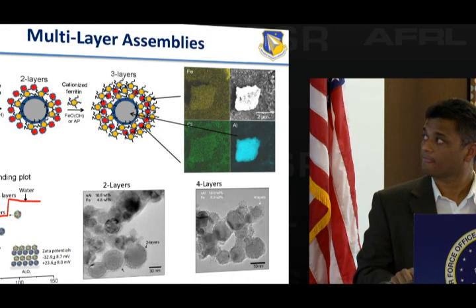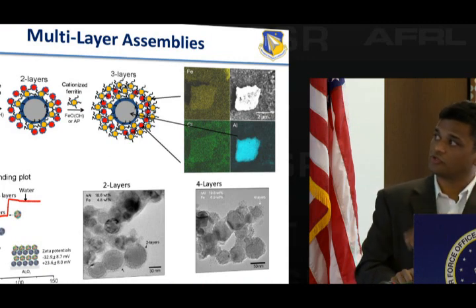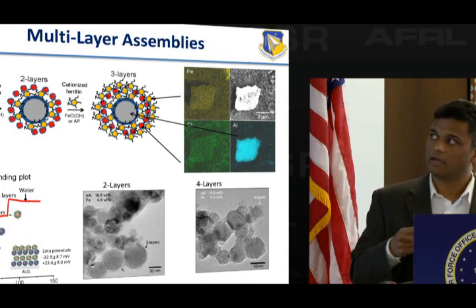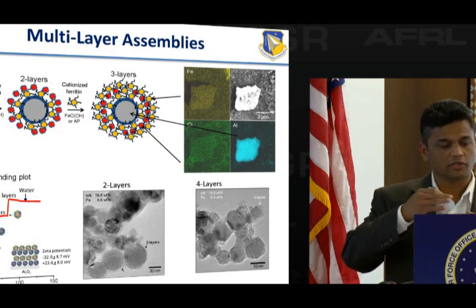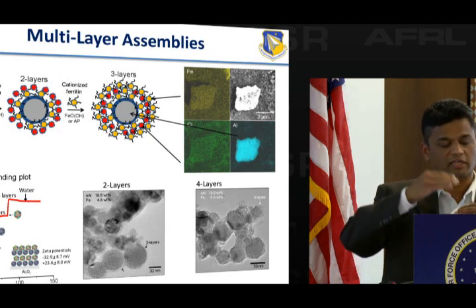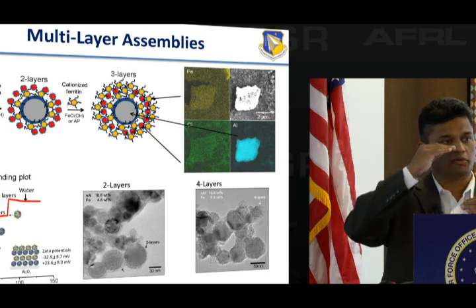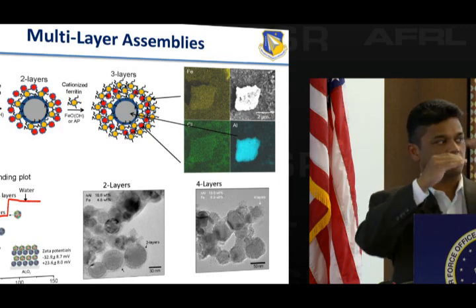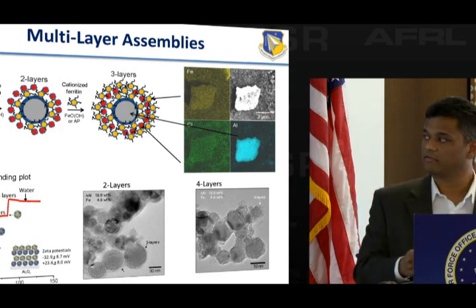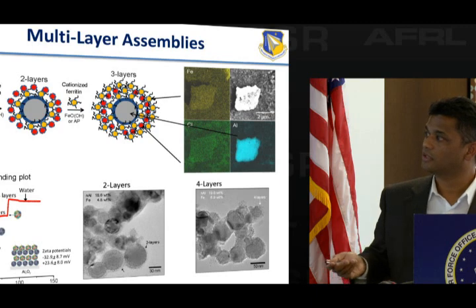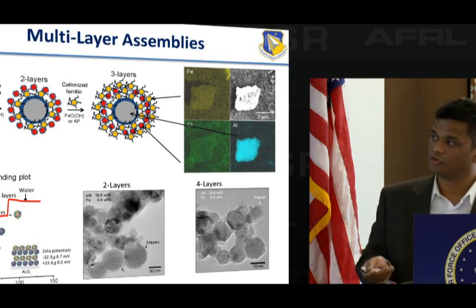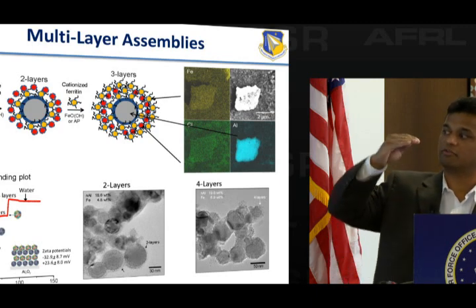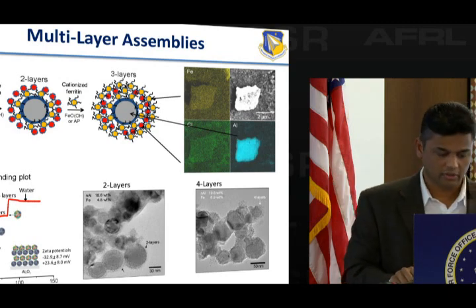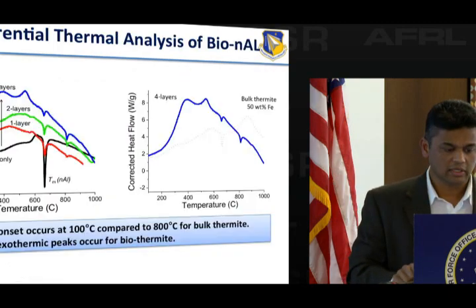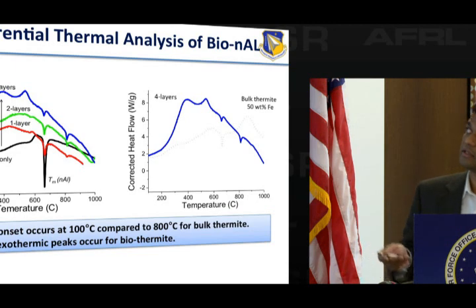We have done EDS mapping to show things, but we've been able to show that you can not only create one layer, you can use rational design to create multiple layers. You can put ferritin, you can put ammonium perchlorate, you can put ferritin, and build the layers very nicely. You can go from 2 to 4 layers. This is showing the mapping, and this is showing QCM, showing that the mass increases with every layer we put onto that surface. We've done zeta potential measurements,